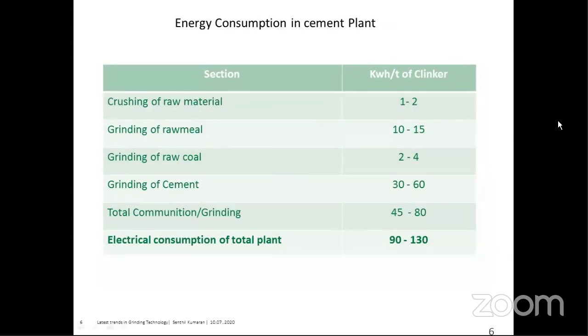Here, crushing of the raw material takes 1 to 2 kilowatt hour per ton of clinker. Grinding of raw meal takes 10 to 15 kilowatt hour per ton of clinker. For coal grinding, it is 2 to 4. For cement grinding, it is 30 to 60. So total comminution, grinding alone, is 45 to 80 kilowatt hour per ton of clinker.